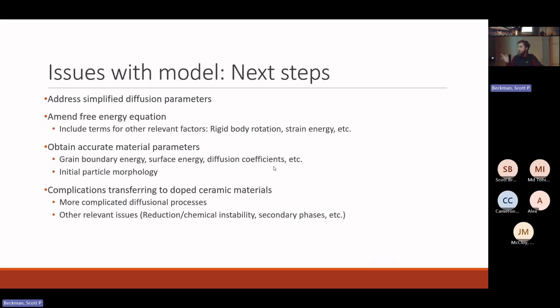Now, the issues with this model as it stands is—well, there's a lot of them—but a few of the key ones are the diffusion, which is what defines the motion of material in the system, is rather primitive. I simplified their model even further, assuming that the only diffusional process that exists is volume diffusion. But this is not accurate, and both surface diffusion and grain boundary diffusion, which have different weights, will have high relevance on the actual sintering of these particles.